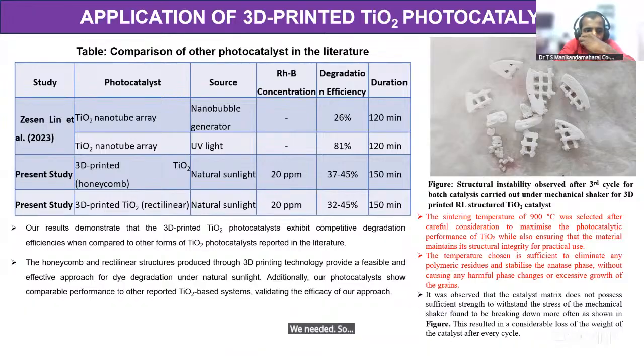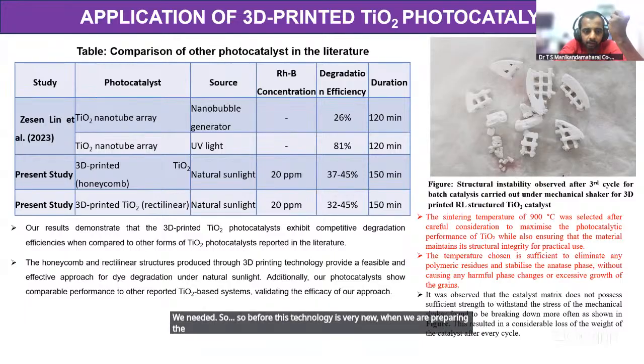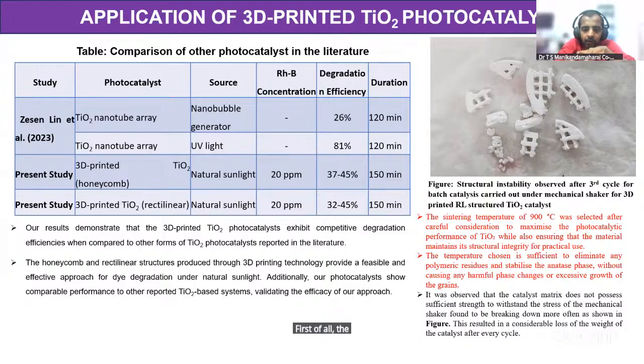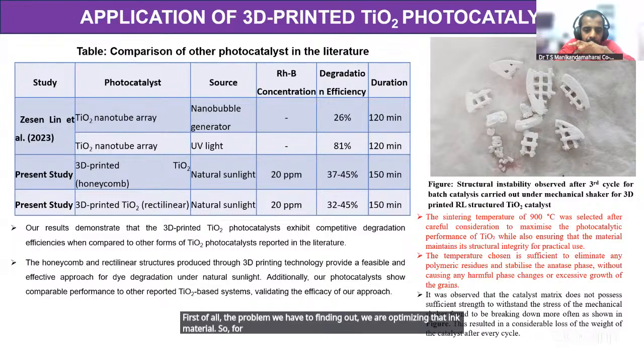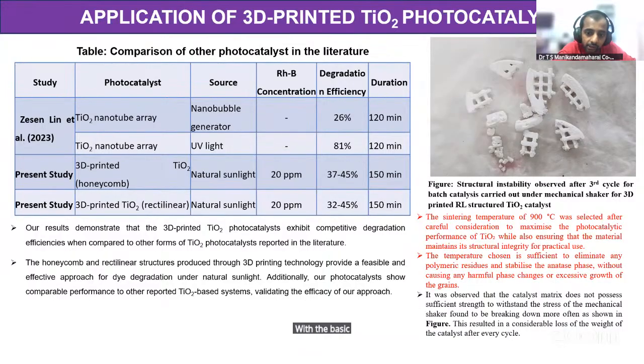This technology is very new. When we are preparing nanotube material, producing even 100 grams is so difficult. So the solution we found is to take the basic stock material of TiO2. First of all, we have to optimize the ink material. We optimize the ink first with the basic material, and then see how that material performs. That is what we focused on. With the basic material itself, ink optimization is done.